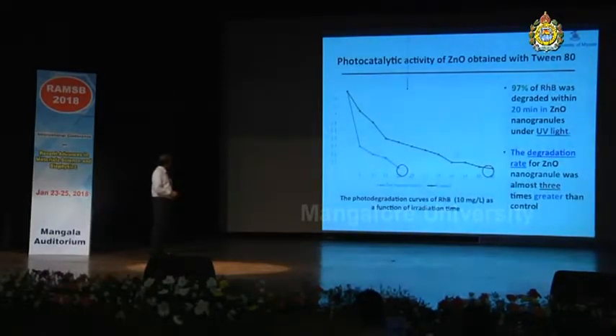And we have tested the photocatalytic activity of zinc oxide with Tween 80, and we have achieved about 97% of rhodamine B degraded within about 20 minutes in the presence of these photocatalysts, zinc oxide granules, under UV light. And the degradation rate for zinc oxide nanogranule was almost 3 times greater than the control sample.